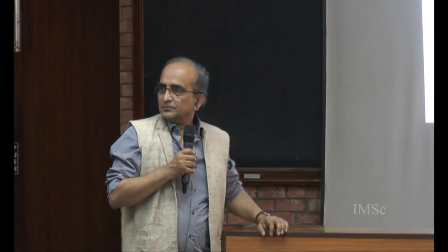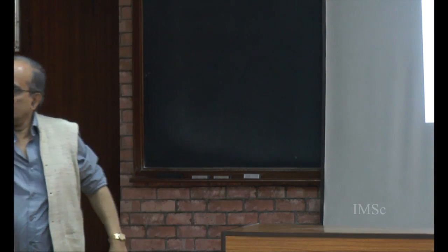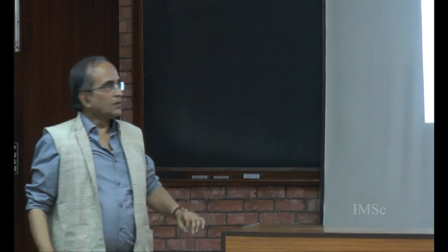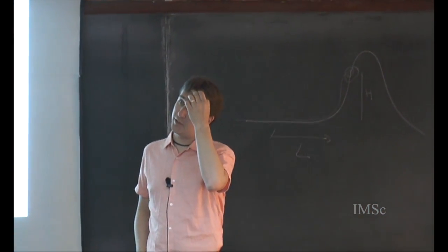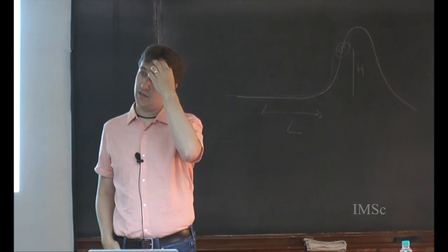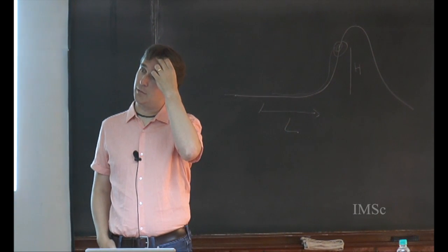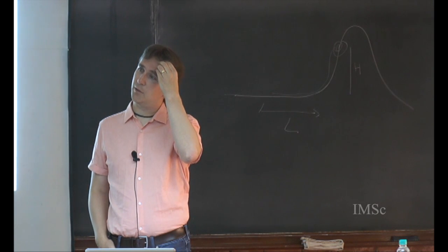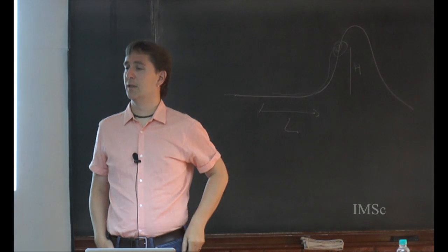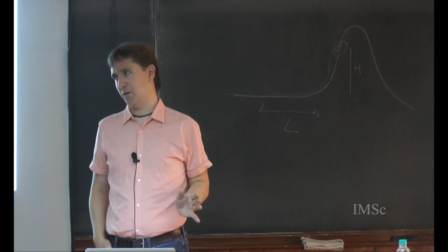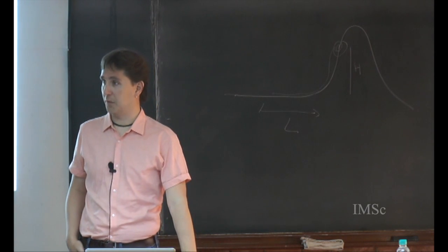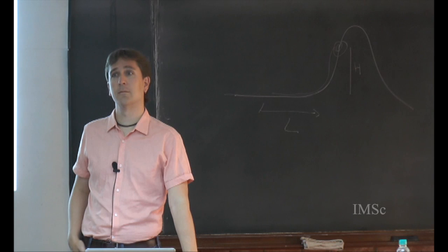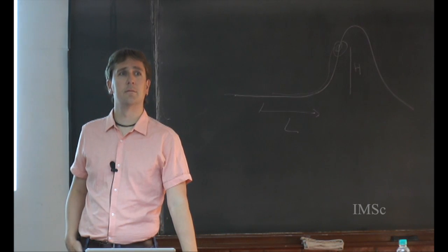Will there be any effect on the plasticity of the beads for polydisperse? We didn't seriously explore that. We did compare the monodisperse case where we had precision beads of about 1% to the ones we get by default, which are about 15%. There was no obvious difference, but it's not something we explored rigorously. It shouldn't be a first order effect, but there should of course be some subtleties in that, even changing packing fraction, for example. Other questions?